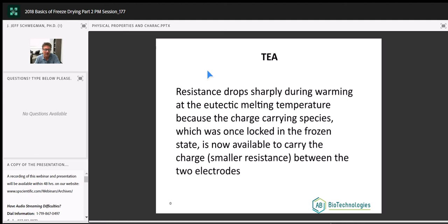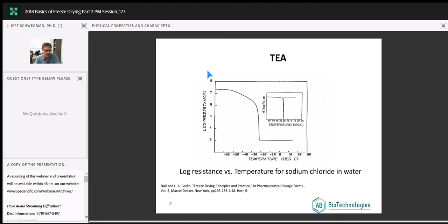Okay, we talked about the resistance dropping sharply as we go through the thermal events. Down here, we're frozen, negative probably 70-ish. High resistance, as we warm, boom, we see this big drop in resistance. We take the second derivative, we see a point, so that tells me at about negative 30, if we get too much above negative 30, that interstitial space forms a fluid, and if we try to freeze dry above that, we're going to get collapse.